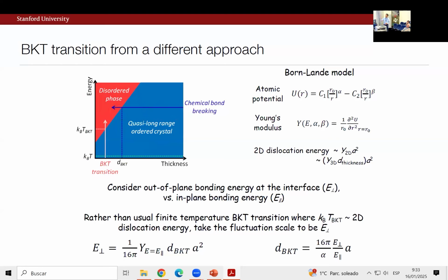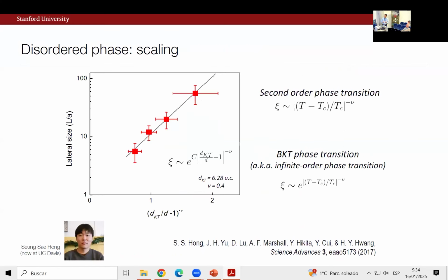So what would be the ingredients? Maybe this view graph is a little bit too busy, but the topological defects are going to involve some sort of dislocation energy. In the thin regime, I can say that energy scale goes as the Young's modulus times the thickness. So as the thing gets skinnier and skinnier, the cost of this defect goes down, down, down. That can represent this line here. So what we think has been going on is that as we dissolve this layer out, we're crossing this abstract phase boundary and catching the collapse of this quasi-crystalline order scale. It's natural that this would map to the thickness, because this goes into the energy cost of this defect.